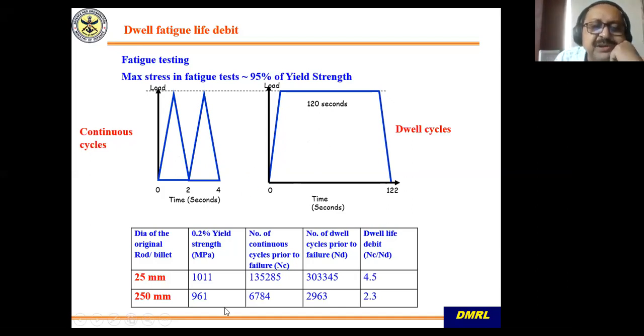Here again I am showing you this table, and the testing is done at around 95% of the yield stress, so that it fails quite fast and you don't have to carry out fatigue testing. Fatigue testing, as you know, is very time consuming. Here I am comparing DMRL developed titanium alloys which were forged to 25 mm dia rods and also to 250 mm dia rods. There is a slight difference in yield strength, and you can see the difference in the number of cycles in continuous cycling.